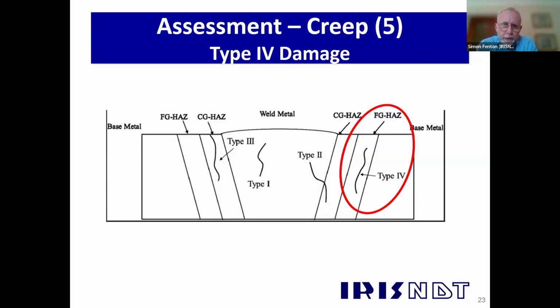Typically in the coarse-grained heat affected zone, we get things like reheat cracks you might have heard of. But my focus for this presentation is on this fine-grained heat affected zone, also known as the Type 4 region. And the Type 4 region is a particularly creep weak zone. If you show me the next slide, Pete, please.